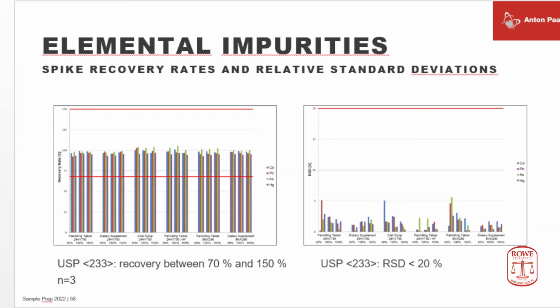And maybe you have missed the mercury in my previous slide, because you know that mercury is the most critical element in terms of losing it out of a digest. So if we would spray out sample solution, we would never find mercury. Finding the mercury indicates that our smart vent system, like explained before, works analytically very well. So we find full recoveries. In the table here to the right, you see the RSDs of these experiments, and they are in most cases below 5, in most cases even below 3% RSD for 3 replicates. So this is just to show you the analytical reliability of the smart vent concept.